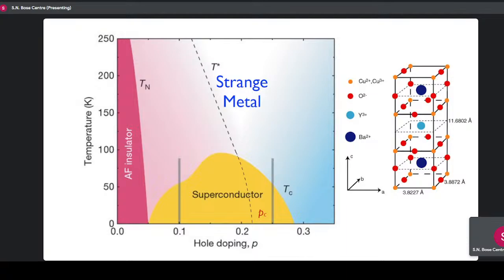So we have these superconductors like yttrium barium copper oxide, which have a superconducting critical temperature which can be above 100 Kelvin or so. One of the big questions, of course, is what is the value of Tc and how do you compute it? Naturally, you would like to put that in BCS theory, but the fundamental ingredient of BCS theory is really Fermi liquid theory. The parent state of the BCS superconductor is a Fermi liquid metal.